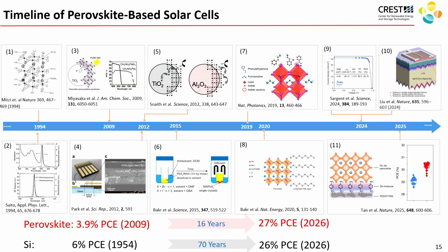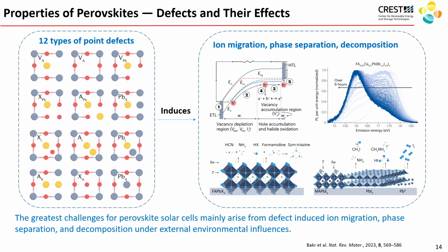However, this defect tolerance, also in the ionic nature of perovskites, leads to formation of many types of point defects. Even though they're electronically benign, they can eventually lead to the rapid chemical degradation of the material, especially when temperature, bias, and light all come together. They can lead to the degradation of the compound and phase segregation, and eventually the breakdown of the device.